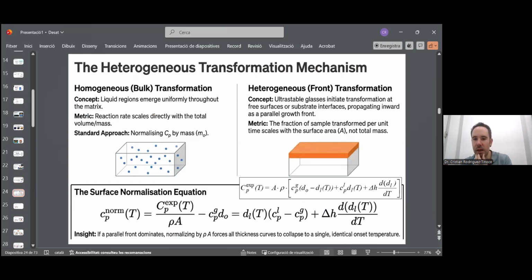But if we have a glass which is transforming, as I was mentioning before, via a front, starting on the surface and propagating into the bulk, we cannot normalize the heat capacity with the mass. Why? Because the whole mass is not involved in the transformation process. Only a layer which is initially very small, and then propagates into the bulk, is contributing to the devitrification, not the whole mass. So what we have to do here is use another normalization protocol to understand the transformation mechanism.